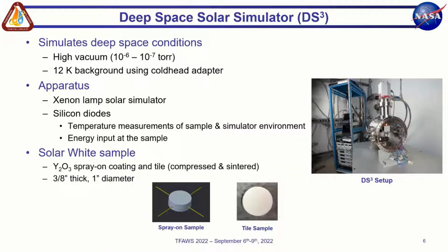Now for the deep space solar simulator, DS cubed for short. This facility is located at NASA Glenn, and this is a picture of it on the right. Most of it is the thermal vacuum chamber, which simulates deep space conditions by establishing a high vacuum of 10 to the minus 6 to 10 to the minus 7 torr. It also establishes a cryogenic thermal background using the cold head adapter, which is shown here, and that drives the temperatures down to about 12 Kelvin.